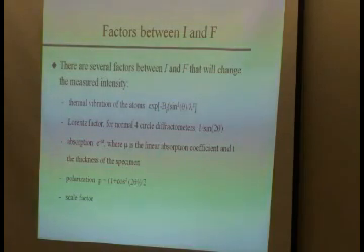You will have absorption. Samples don't just scatter X-rays, they also absorb them. So that reduces the intensity. The function is e to the minus mu t, where mu is the absorption coefficient and t is the thickness. You have a polarization factor of the X-rays. Once again, it's a fairly simple geometrical function. Then you simply have a scale factor, because we lose some intensity. Some of it is scattered by air, some of it is just not detected. So you have a constant with which you have to multiply your data.